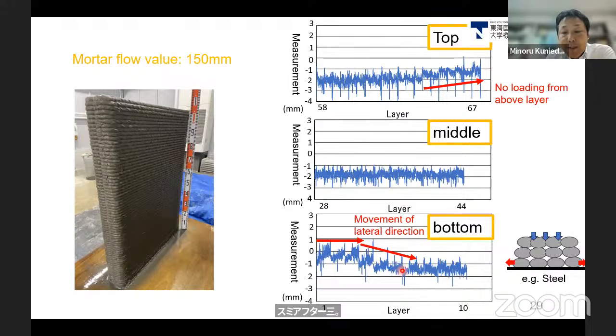negative value was observed because in this phase, the above layers are pushed onto the bottom layers, and the bottom layers have lateral movement from the original positions, because we have the interface between the steel plate and each filament. So the friction or deformation due to the pushing has been observed here. But in the middle part or top part, no change has been observed. But finally, the negative value has improved to zero, because there is no loading from the above layers at the top of the walls, as we can see.